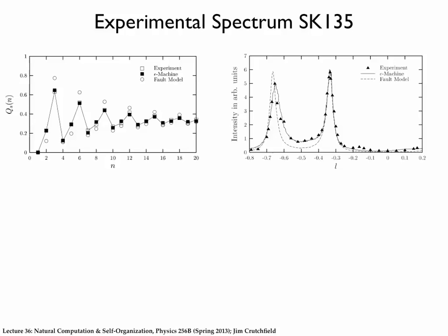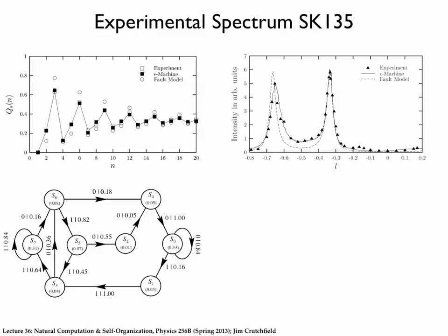And if we look at the epsilon machine, does it conform to what we think? Okay, well, it spends a lot of time at S0. This is 3C. This is what we think of when we think of 3C structure. It spends a lot of time over here in S7. We think of this as 3C structure. So that part looks right. What about the 2H structure? Is there any 2H structure here? Well, in order to get 2H structure, I need to see something that goes back and forth. In fact, this epsilon machine makes a definitive prediction. This epsilon machine says that whatever 2H structure was in this crystal has been completely obliterated, because there's no way I can get any series that goes 1 0 1 0 1 0. It makes a definitive prediction that the 2H structure is gone.